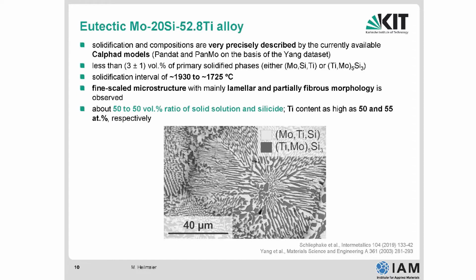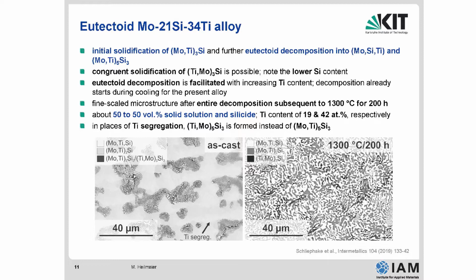We have a very fine-scaled microstructure, and the question is, how does this fine-scaled microstructure perform at elevated temperatures with respect to creep and with respect to oxidation resistance? Compared to that, the eutectoid alloy, you can see, has a much higher molybdenum content. Here, silicon plus titanium together is about 55, so that means 45 atomic percent is still molybdenum. And I said previously, at the beginning, this is the as-cast microstructure. The as-cast microstructure did not fully decompose into the thermodynamically stable phases. That's why we needed this 1300 degrees Celsius heat treatment. Here you see this light gray phase. This is still Mo3Si, and you need to decompose this into the stable phases, the molybdenum solid solution and the Mo5Si3 phase, which has been done here. Of course, you note that there is some residual Ti5Si3 here, the very dark phase, but this is only to a minor content, 5.2.